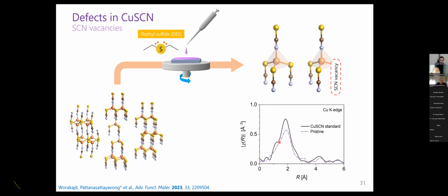So in this case, we think that this is because of the SCN vacancies. What we think happens is that after spin coating, the diethylsulfide copper thiocyanate is in a wet state. And then during spinning, some of the diethylsulfide leaves, and the film becomes like a gel state. But inside, there's a mixture around copper of the thiocyanate ligands and also the DES molecules. And before it solidifies completely, some of the DES molecules are still trying to leave. And that basically leaves some vacancy states inside the CuSCN material.